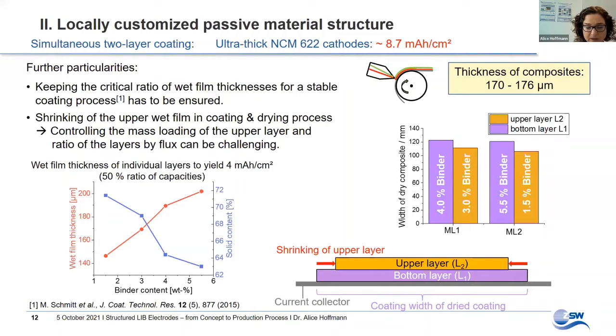In our experiments with ultra-thick cathodes, we observed that the upper layer was 12% smaller than the lower one, as illustrated in this sketch. This means that the mass loading contributed by the upper wet film can also be 12% more than intended. This deviation is not negligible. However, it is still much lower than the failure of 38% that we calculated would have resulted without a customized wet film thickness.